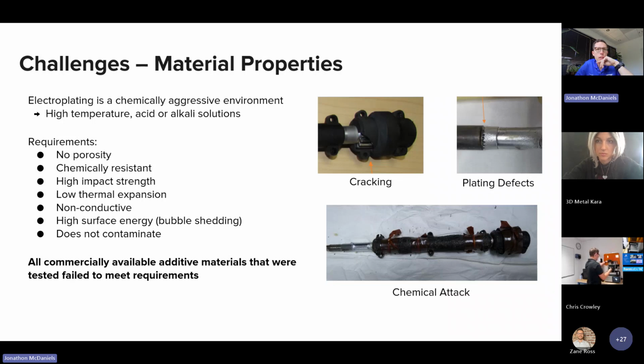And then the last requirement is that it does not contaminate the bath. This is really a lot of times unique to electroplating, but a lot of materials that you would use in other processes are big no-nos for electroplating. Something like a silicone oil or a plasticizer, if it leaches out, is going to cause adhesion failures. And then your entire 1,500-gallon plating bath has got to get dumped, and you've got to put a brand new one in. So it's really important that this 3D printed material does not contaminate the bath.